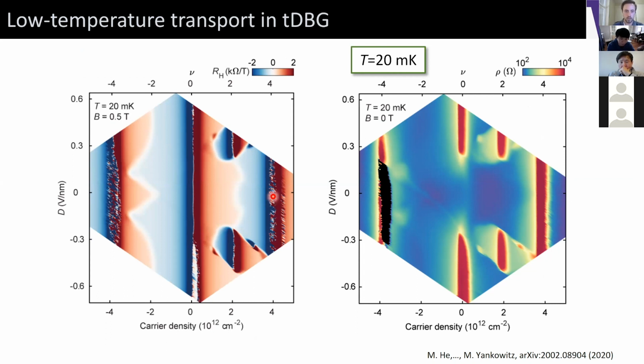What I'm showing you is a Hall coefficient, and really you just need to concern yourself with whether the color is red, white, or blue. Red tells you that you're measuring electrons, blue tells you that you're measuring holes, white tells you that the system is roughly balanced between the two. So we see sign changes as we anticipate across the neutrality point and across full filling of each of the